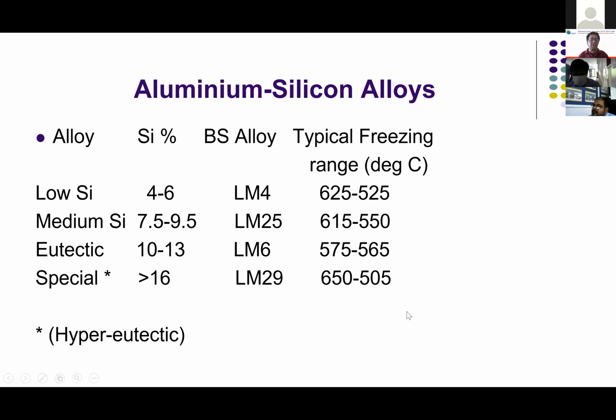These are the basic major aluminum silicon alloys. One is low silicon alloy LM4, where the silicon is 4 to 6%, medium is about 8 to 10, 7.5 to 9.5, LM25, AC4C, very widely used. And then eutectic alloy 10 to 13%. Again, this is very widely used, LM6 and LM24, etc. They have 10 to 13% silicon.